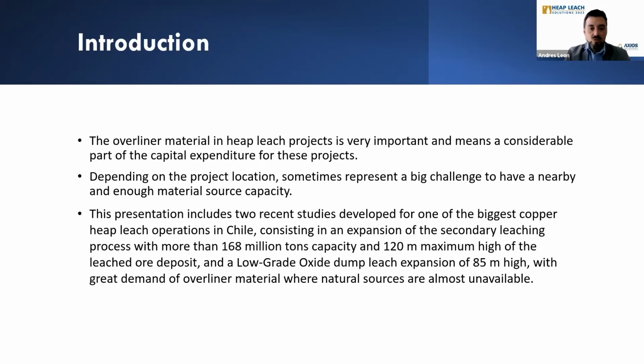This presentation includes two recent studies we developed for one of the biggest copper heap leach operations in Chile, consisting of one expansion for a secondary leaching process with more than 168 million tons capacity and a 120 meter maximum height of the leach ore deposit, and a low-grade oxide dump leach expansion of 85 meters high, with a great demand for overlining material where natural sources are almost unavailable.